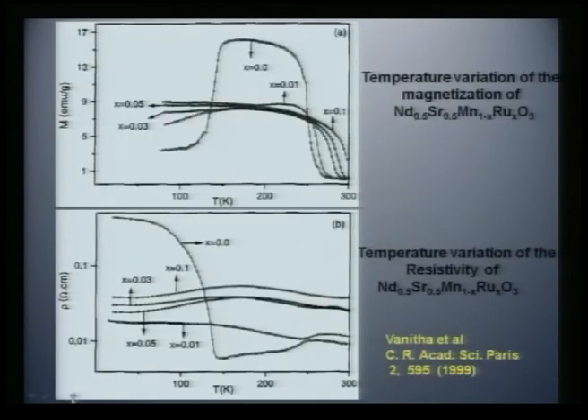But the classic example comes from Professor Rao's group in 1999. They did this work where they have taken the neodymium strontium manganese oxide and they have substituted a little amount of ruthenium. What is the amount of ruthenium that is added? It is 1%, 3%, 5% and they have gone up to 10%. What is interesting here is the moment you start putting just 1% of ruthenium in this charge ordered magnet, immediately this charge ordering is removed and the system becomes a ferromagnetic metal.